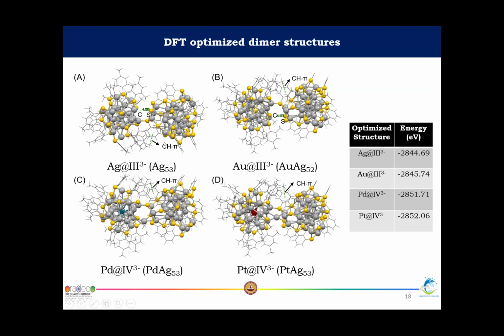Yes, but my question is, these dimers are forming and are stable in the gas phase, under the soft ionization condition of the ESI, not harsh. But CH-pi interaction is not that strong. So what if there are other types of interactions occurring between the clusters that have some impact? Like Deepak was also telling, CH-pi interaction is very weak, right? So it is surviving in mass spec conditions. That's what my doubt was. Is there any other interaction?